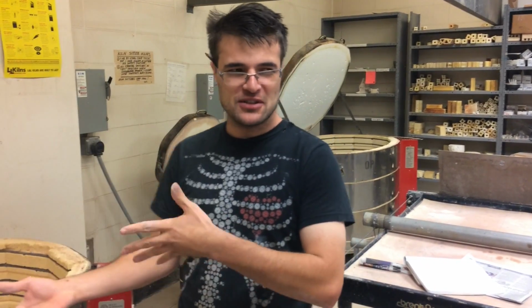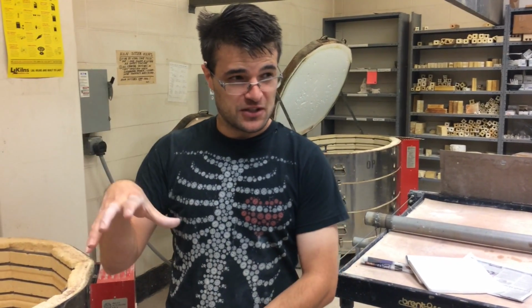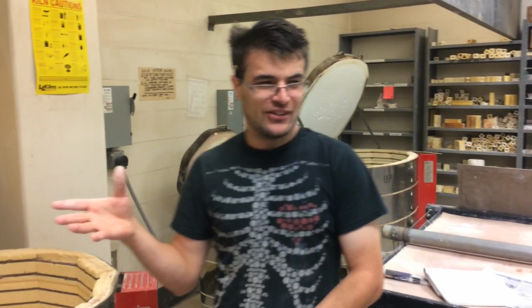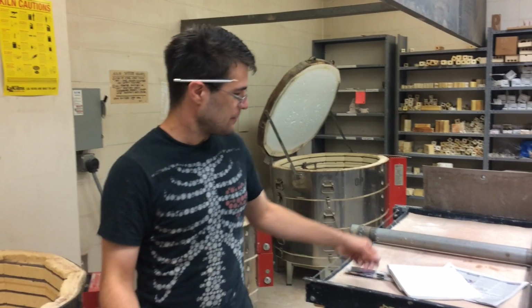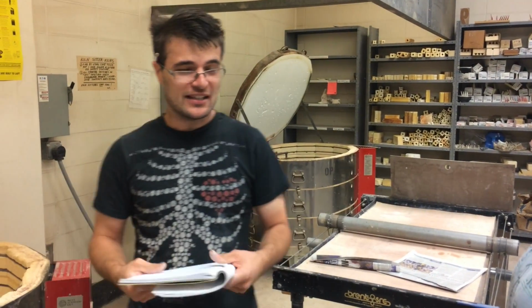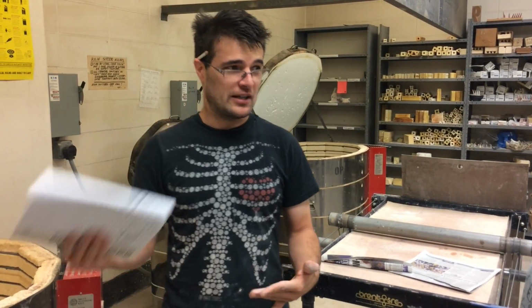And also during the time you can see an odd growth and shrinkage of the work, but it's only like 0.3%, so not enough to really matter. But clay by itself, depending on the type, can shrink anywhere between 8% total to 20%.